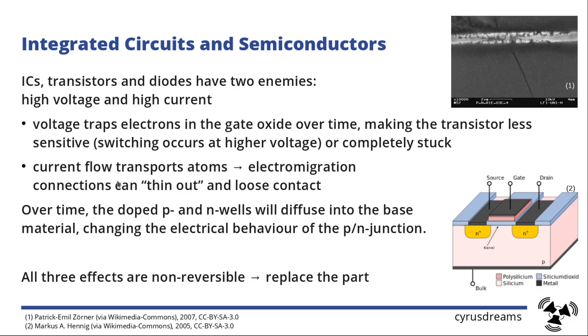There's a second way of damaging those parts, that is, we have the current inside here. That's called electromigration. It transports the atoms around, so you start off with a proper trace like that one. But in this case, on this position, something is wrong with that trace. Either it had a thinning already from production, or there is some special heat up here, whatever. But what will happen is that the current will transport material from that running trace to somewhere else. And the connection thins out and it just loses contact completely. So that device is then now not functioning anymore.